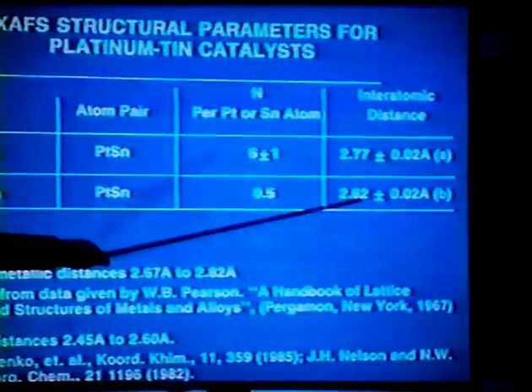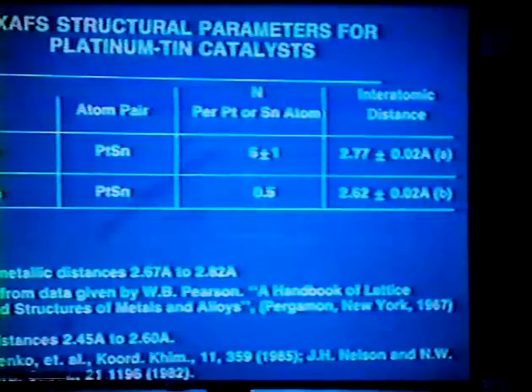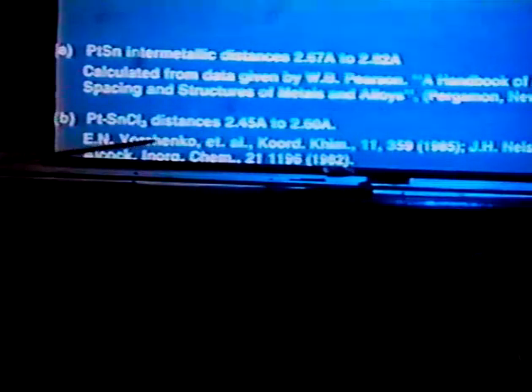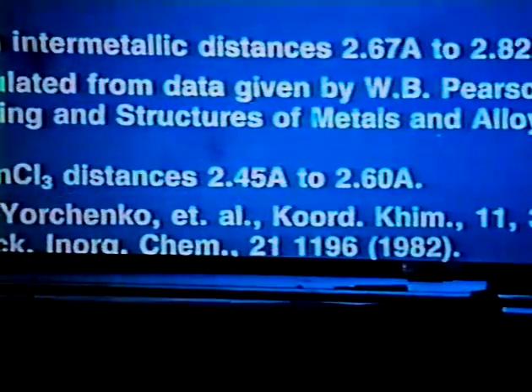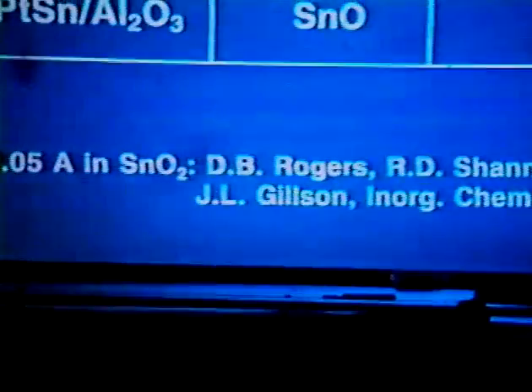Now, on alumina, we get something else. We get this very short platinum tin distance. And by the way, this is a small number, but it's not indispensable. It's a real number. We get this 2.6 angstrom platinum tin distance. Well, where does that occur? There are a number of coordination complexes where platinum has SnCl3 ligands. And in those various complexes, you see platinum tin distances in the range of 2.45 to 2.6 angstroms. So whereas platinum doesn't see very many tin atoms in here, those that it does see are at a short distance, characteristic of this kind of covalent bonding. Next slide, please.